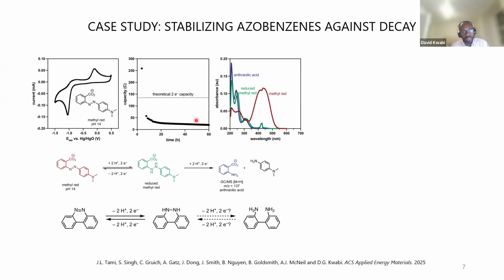Now, by applying our spectroscopic analysis to the electrolyte as it's undergoing cycling, we found that it's in the reduced form. So after we've reduced it, we end up with this form. We actually end up with a breakage, or if you like, a cleavage of this nitrogen-nitrogen bond, and we end up with two fragments that are not active in our battery. So the nitrogen-nitrogen bond is sort of weak, it cleaves, and then we end up with capacity decay.